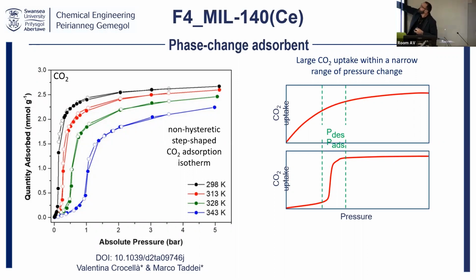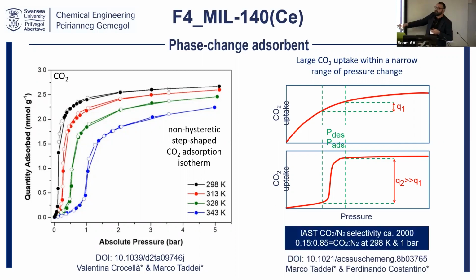Now, the working capacity of the material is between these two pressures. So from the amount of CO2 that I have on the surface at the adsorption pressure, to the amount of CO2 that is left after I reduce the pressure. The amount of CO2 recovered is Q1. You can see from this that if you have a jump like that, you can fundamentally increase the working capacity of the material. The material also has a very high selectivity, 2000. So for each molecule of nitrogen, you absorb 2000 molecules of CO2.